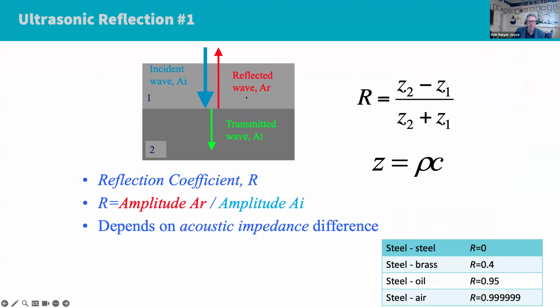It basically works on a reflection principle, like you can see here. If you put an ultrasonic sensor on top of the bearing raceway and send a sound wave through, ultrasound reflects back at interfaces. And the more acoustically different the materials are, the more that's reflected back. So we have this thing called a reflection coefficient, R, which depends on the difference in density and speed of sound between these two materials.